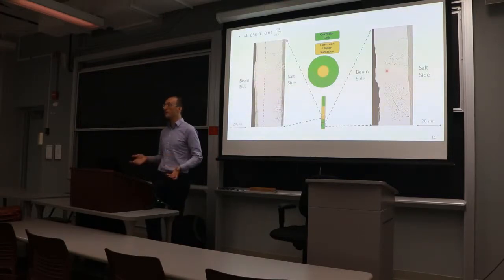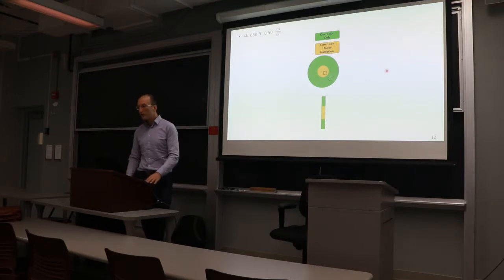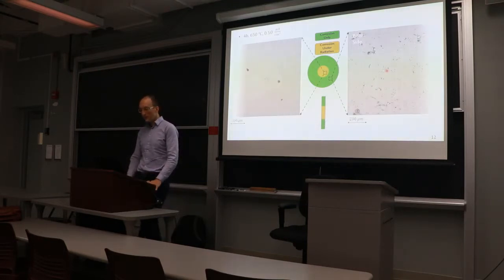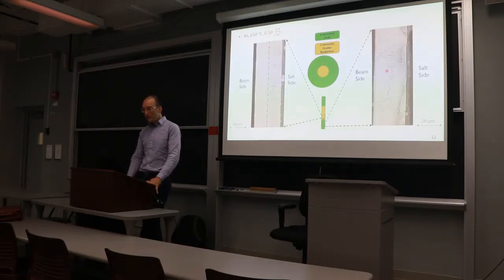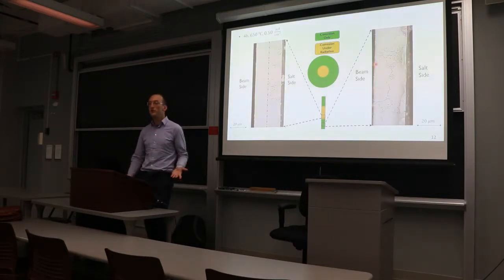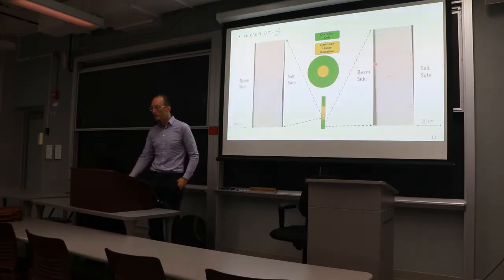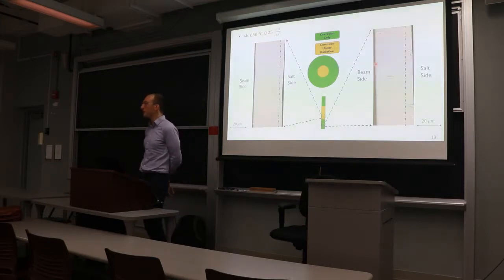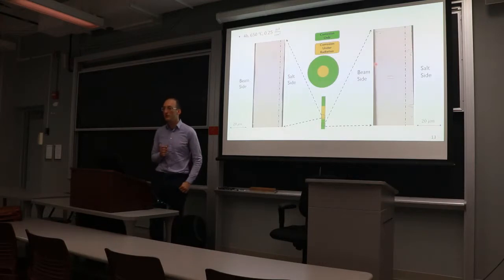It's not an acceleration. Lowering the proton beam current a little bit, same picture on the front, and in the cross-section you see that the salt didn't quite penetrate as far on the irradiated side, but also got all the way through on the unirradiated side. Cut the proton beam current in 2 again. Everything looks clean on the front, but the cross-section reveals about double the penetration in the unirradiated side once again. And so there are 2 competing effects going on here.